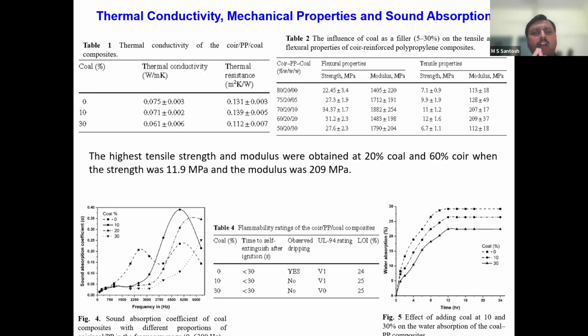So these results clearly indicate that any ratio between 60 to 70% of coir and 20 to 10% of coal, along with polypropylene, would be a suitable composite to maintain substantial strength, in order to make sure that these are utilized for suitable applications, for interior applications as such.